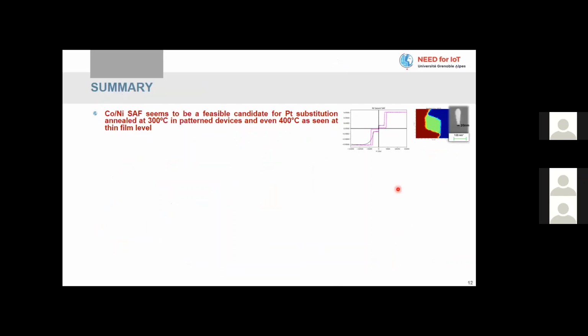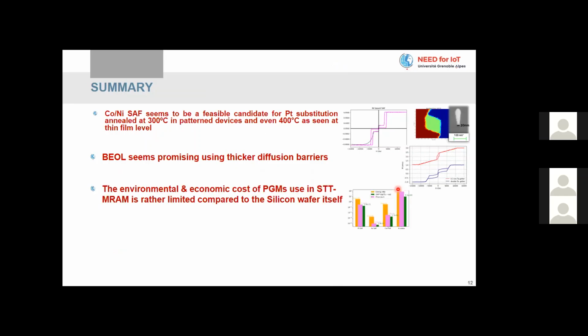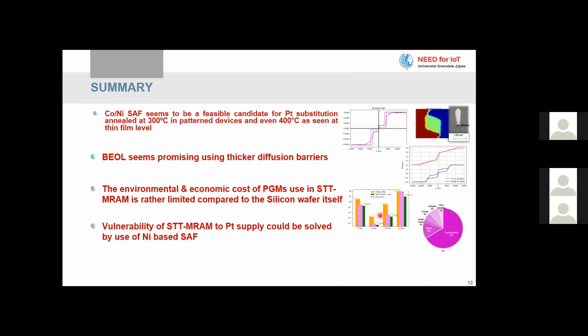So I've shown you that the substitution of cobalt platinum by cobalt nickel is a possible alternative for the SAF of the magnetic tunnel junction in STT-MRAM. We have demonstrated that it is possible to have a good back-end of line compatibility for CMOS integration by protecting the cobalt nickel multilayers from some element diffusion like iron, and that actually the impact of this substitution is not so high in terms of environmental impact, but there's still the question of supply risk that can really be mitigated by having these alternatives.